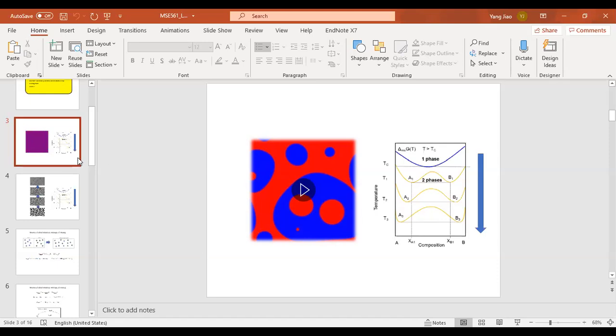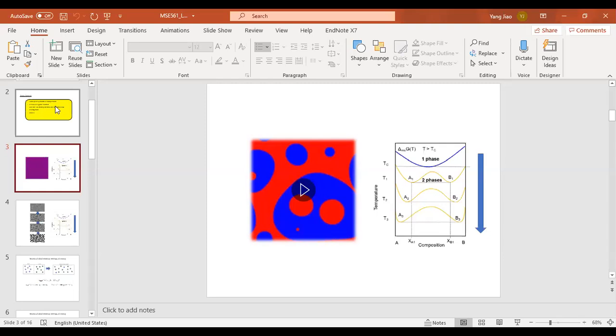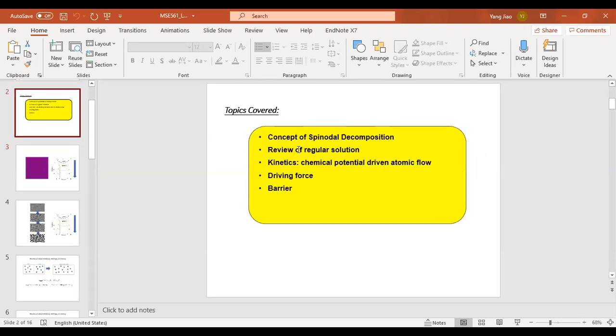I think this is all I want to tell you about spinodal decomposition. Again, this is just a quick recap of the topics. We introduced the concept, we revisited the regular solution model, which is beautiful for studying spinodal decomposition, and we talked about the driving force and barrier. In the kinetic part, we showed that this is an excellent example of uphill diffusion, where the flux of atoms is driven completely by the chemical potential gradient and has nothing to do with the concentration gradient. So that's all I want to say about spinodal decomposition.